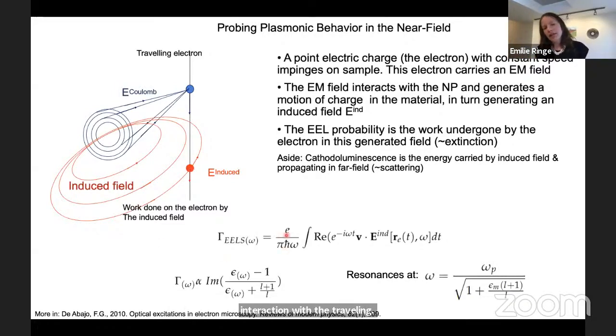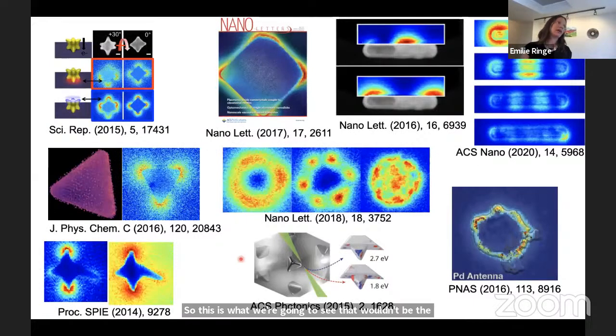You can calculate the loss probability from that, and it's all related to the refractive index inside the particle. You basically get a high loss probability at the plasmon resonance because it's very highly polarizable at that point. So this is what we see when we do EELS. We've done a lot of EELS and maps, and I'll explain what these maps mean through my talk.